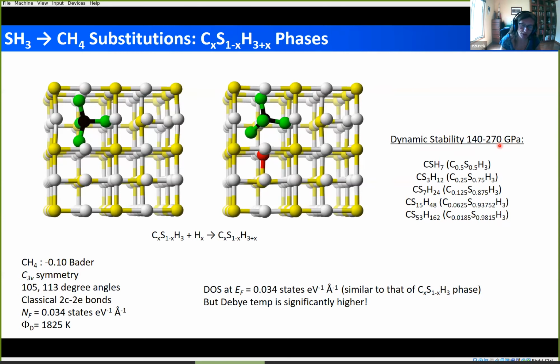We also considered what would happen if you added one extra hydrogen to the sulfur-hydrogen lattice. At least for the models we considered, we found the enthalpy of formation to be too positive, and we think that is due to the steric hindrance between the methane and all of these hydrogens attached to sulfur, which just increases the volume and is not favorable.